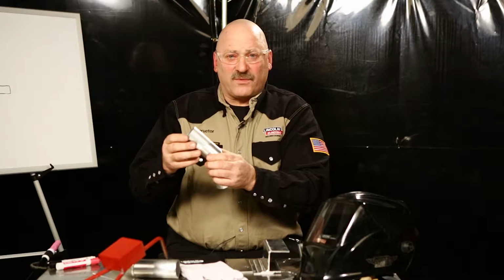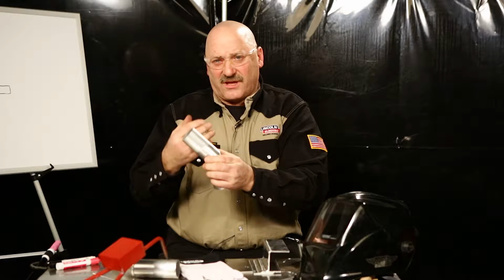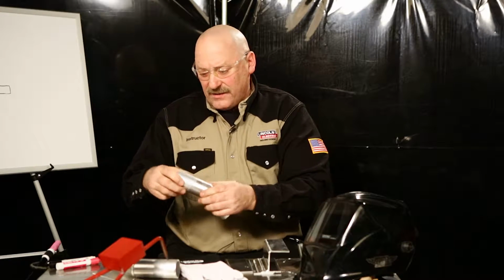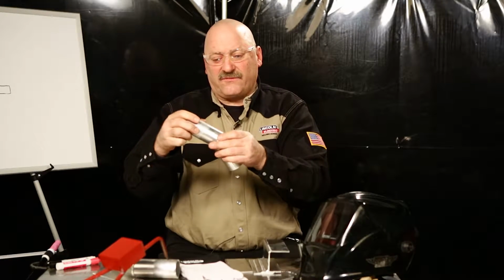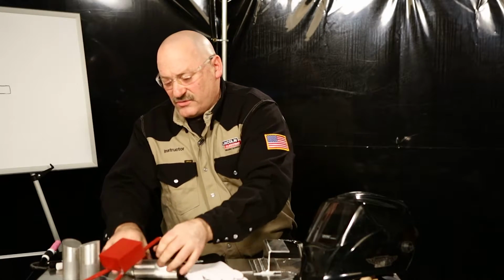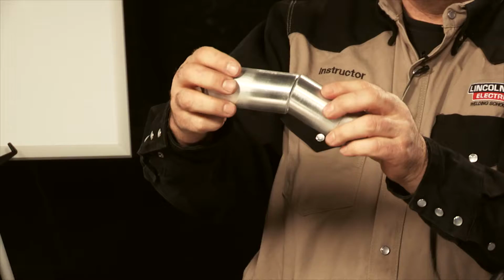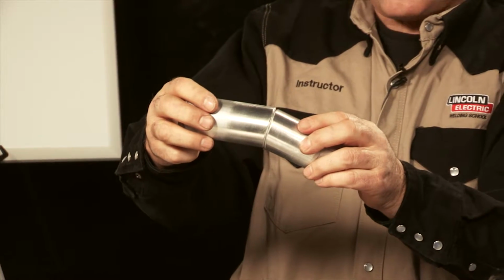And by adding a filler metal of a different composition, we can change the chemistry of that weld metal and not get that crack. So the recommendation here, if we're going to miter and fit these two pieces together, is we will bevel the two pieces, and that'll allow us to get plenty of filler metal in that composition.